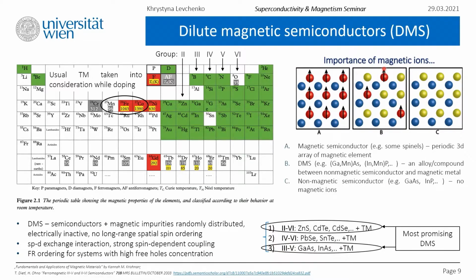So we can add to the already well-discussed gallium arsenide some transition metal, and we arrive at something called a dilute magnetic semiconductor, a new class of materials. Among many semiconductor spintronics materials, magnetic semiconductors in general have attracted much attention and been studied worldwide. Why? Because the ternary, which means that this compound consists of 3 elements, gives the possibility to tune or change the lattice constant and band parameters by changing the composition of the material. And the random distribution of magnetic ions over the cation sublattice leads to important magnetic effects.